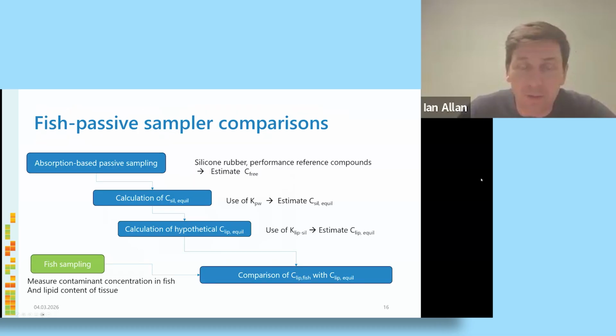Next slide, please. What we've tried to do is to assemble data sets that existed on fish and passive sampler comparison. The first step in this comparison is absorption-based passive sampling with silicone rubber and performance reference compounds to estimate Cfree. In all cases, the same partition coefficients were used for each of the chemicals that we looked at. Then we've got a Cfree, and we calculate a concentration in silicone at equilibrium with the water.